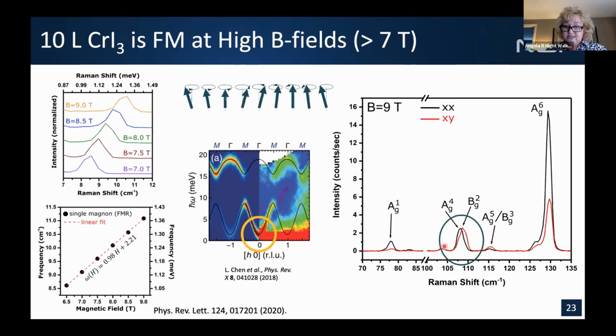What's interesting, though, is at 9 Tesla, we lost our features, the P1 and P2. They're just gone. However, we're still in the monoclinic phase. Also, neutron agrees with this very low frequency magnon seen at gamma at angular momentum equals 0. So we were confident about that feature. We were baffled as to where the P1 and P2 went.